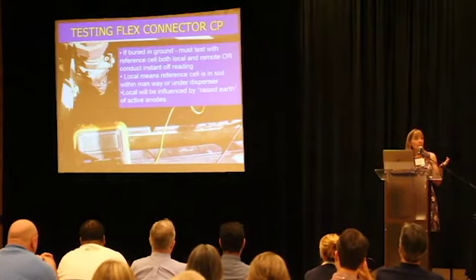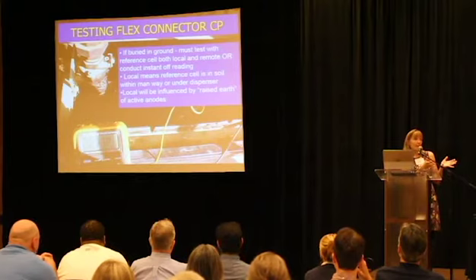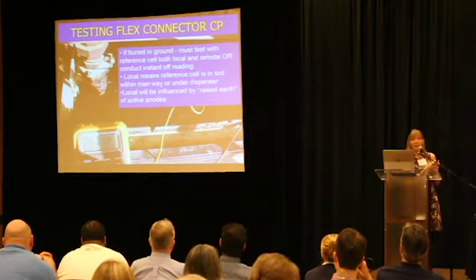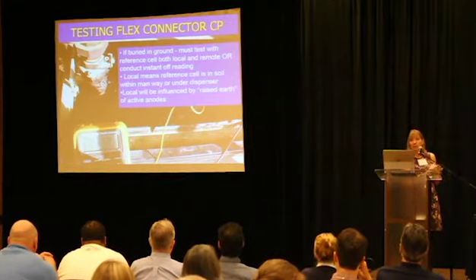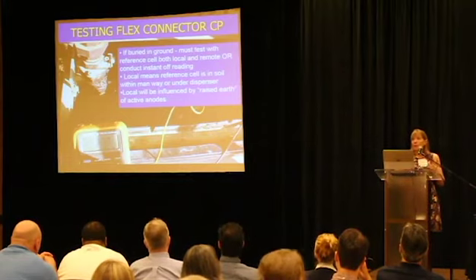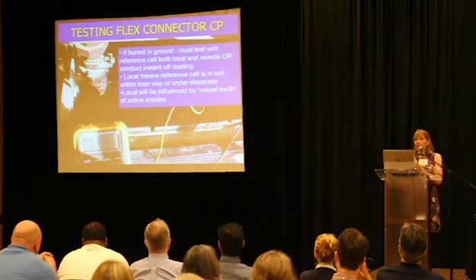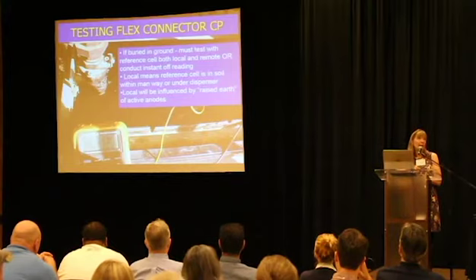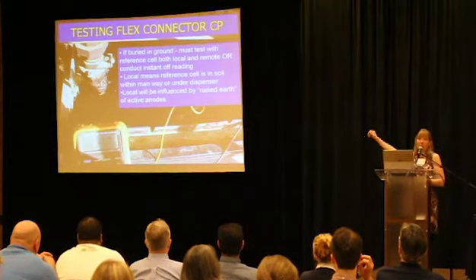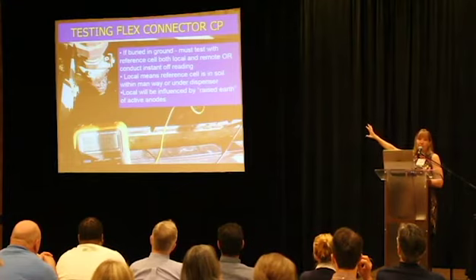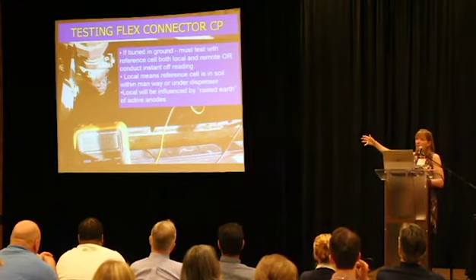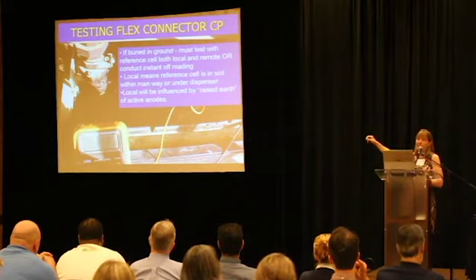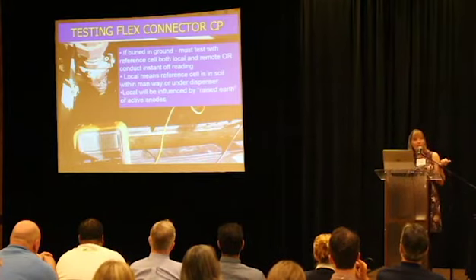And what we would like to see is, if they're not in a contained area, otherwise, they probably aren't going to need flex connectors, although, as I said, sometimes there is soil or backfill material in some of these contained areas. So for these flex connectors, we want to see two readings, one in the local area, and if you're within 12 inches of that anode, it sure as heck better pass. I mean, there's really a problem if it's not going to pass if it's right there. And we'd also like to see a remote reading, so that reference cell placed further away. And that's, again, because where you're placing that reference cell is right next to that anode. So we want to see the local and the remote.